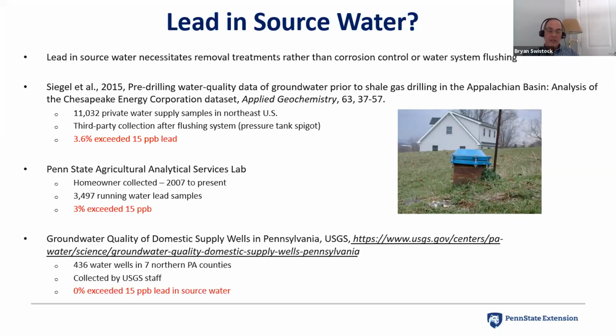And then another data set is a USGS data set that's been looking at water wells in northern Pennsylvania. It has almost 500 samples now in 7 counties. And these were collected very professionally. Nobody knows how to collect samples better than USGS, specifically groundwater samples in this case. And in that particular study, they found that 0% of those groundwater wells had lead above 15 parts per billion, at least. Now, they did find some detectable levels of lead in other samples, but as far as having levels actually meeting the action level, it did not occur. So, I mean, my gut feeling and my perception of this is it's somewhere between 0 and 3%.